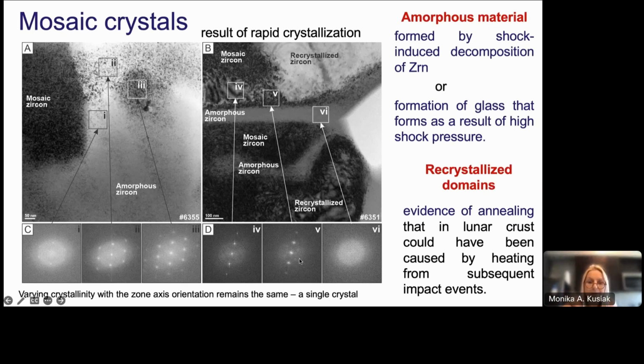And then going to the right, to the 5th square here, we can see that the diffraction spots become fuzzier and broader, and the rings are more diffuse. We think that these recrystallized parts of the zircon were growing at the expense of the mosaic crystal, and then finally partially replaced it. Now if we go to the first example on the left, where we have these broad and diffuse diffraction spots, in the background we can see strong diffuse scattering intensity. So we know we deal here with amorphous material.